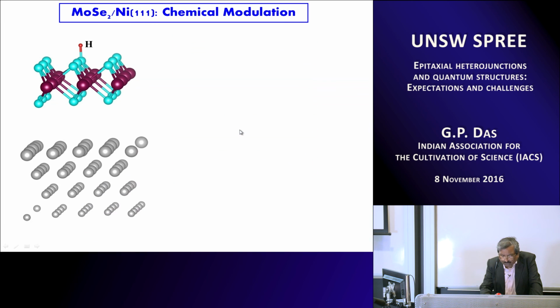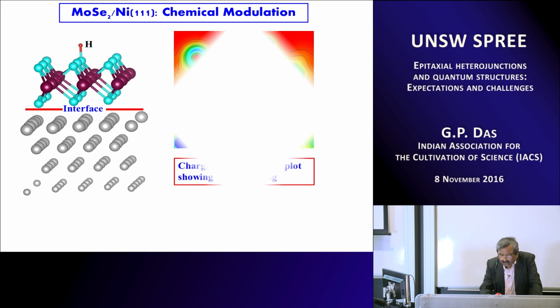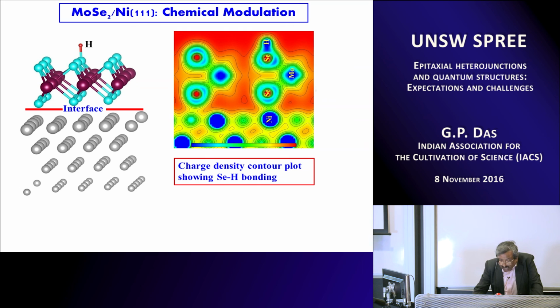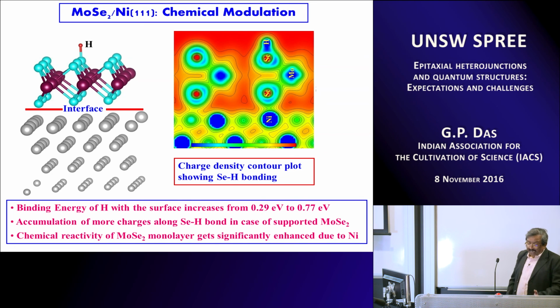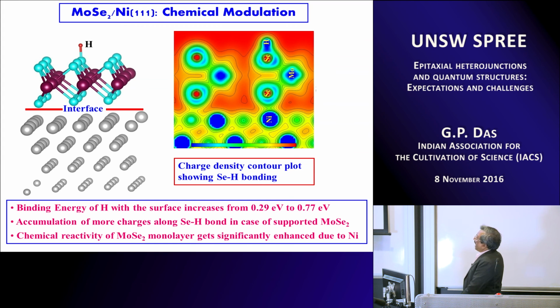Now what I do is that I put the nickel substrate and the interface, and again redo the calculation. Now the charge density of the substrate is also appearing here, and the interesting part is that there is a resulting change in the strength of the bonding between selenium and hydrogen. And how much is it? It is pretty huge. The binding energy of the hydrogen with the surface increases from 0.3 to about 0.8 electron volt. And there is an accumulation of more charge along the selenium hydrogen bond in case of the supported MoSe2. And the chemical reactivity of MoSe2 monolayer gets significantly enhanced due to the presence of the nickel substrate.